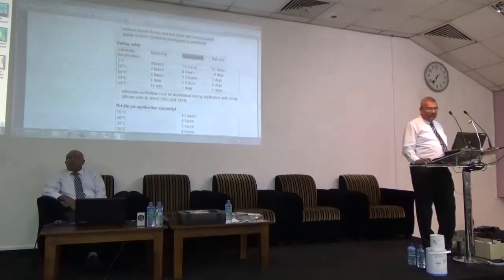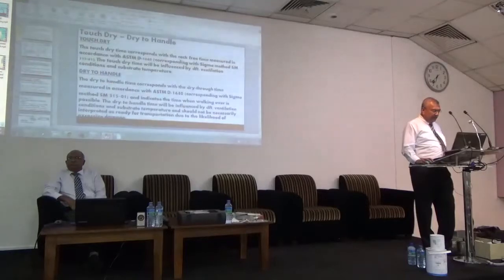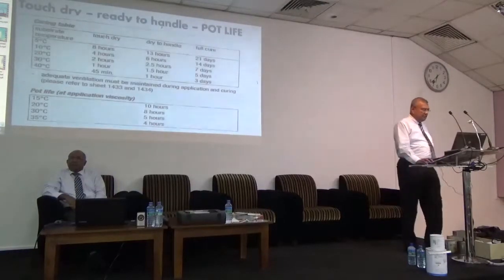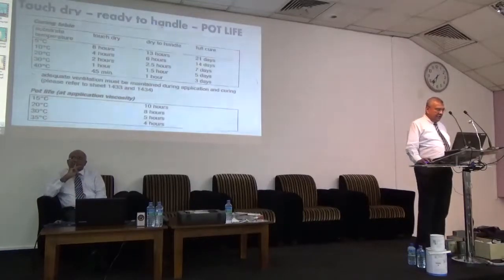So this is what we saw: touch dry, 45 minutes at 40 degrees centigrade and 1 hour at 30 degrees centigrade. But your dry to handle is 1.5 hours. Otherwise you have finger marks all over. Then you have to have rework, then you get paint. So it's all cost.